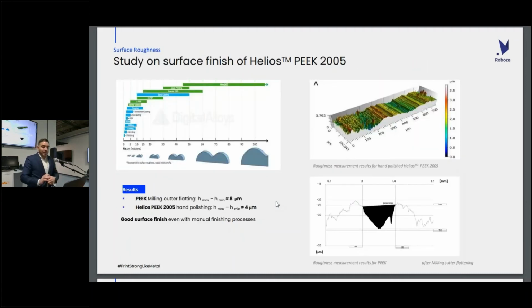And we have here a visual representation. You see that if you take a PEEK part and mill-cut it just with the flat head, you have a surface roughness of about 8 microns. With just hand polishing on the ceramic Helios PEEK, we have 4 microns surface roughness, which is quite amazing. And it takes really little effort.